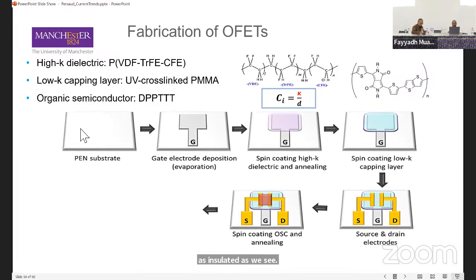So what we do is take a plastic substrate, which can be any material. We deposit a gate electrode by evaporating metal. We spin coat a dielectric on top of that gate electrode. So this is now an insulating material.